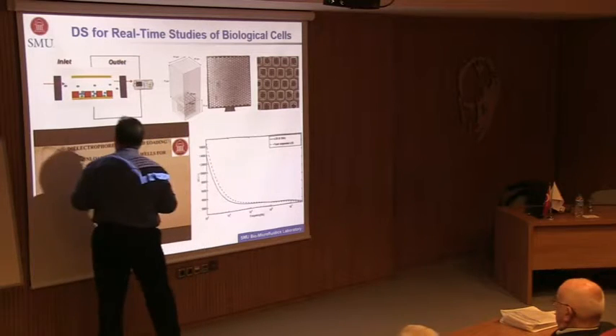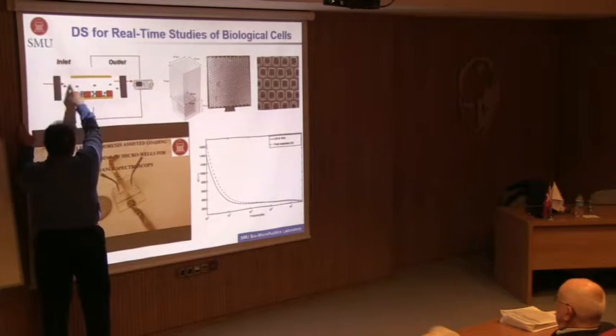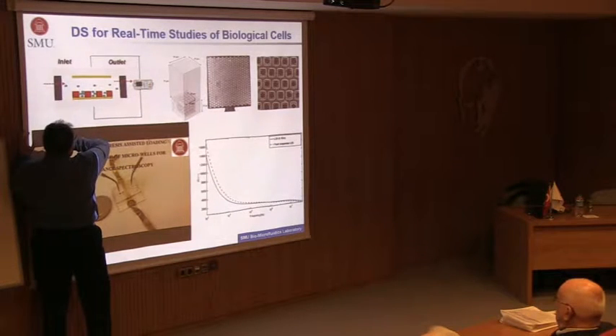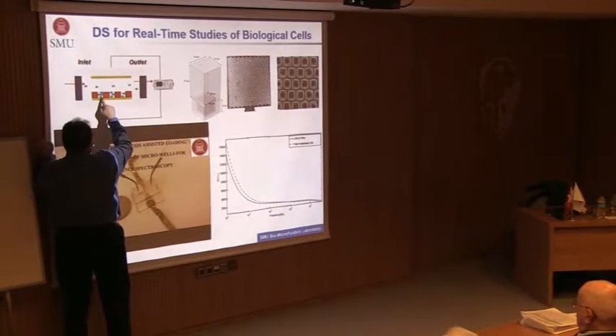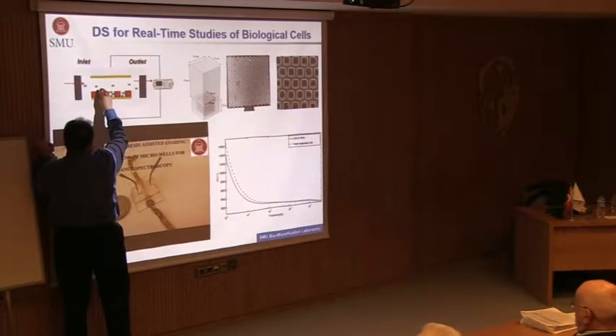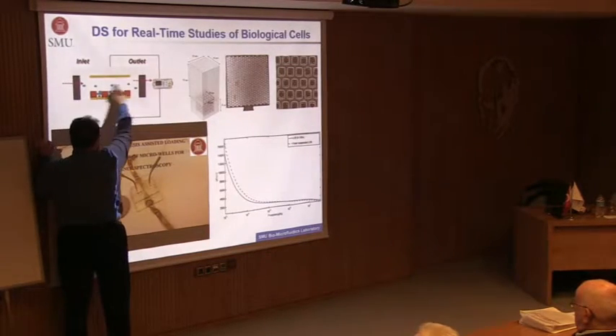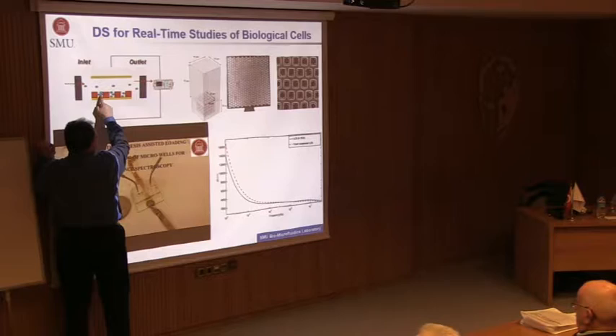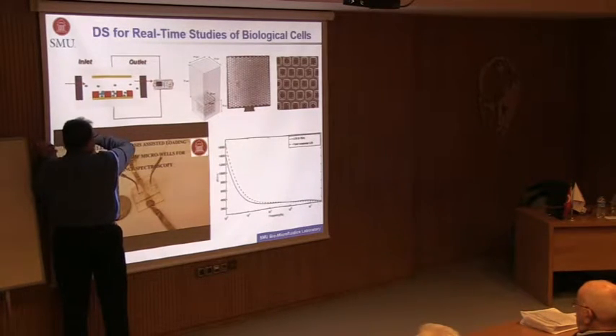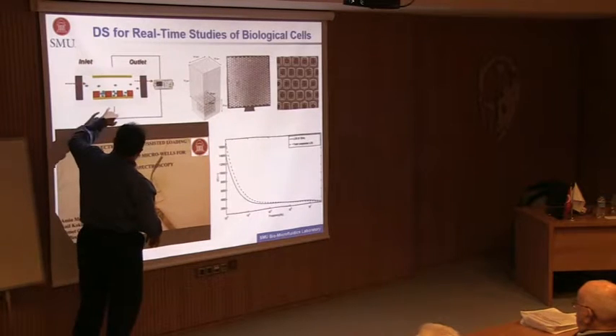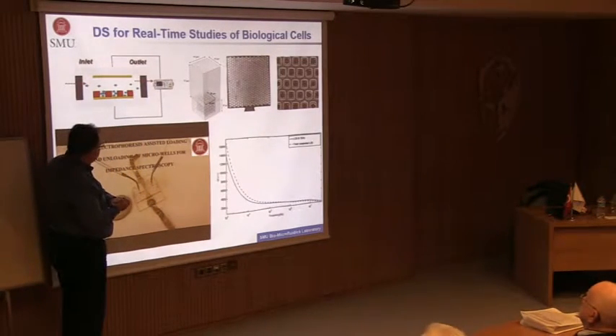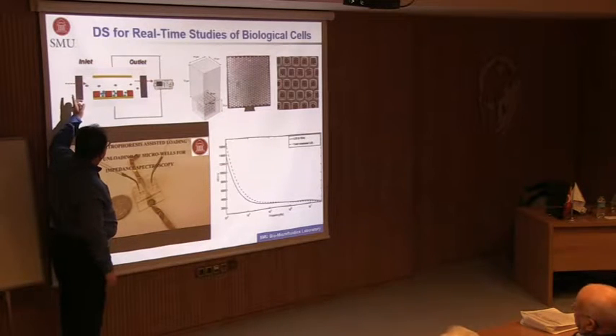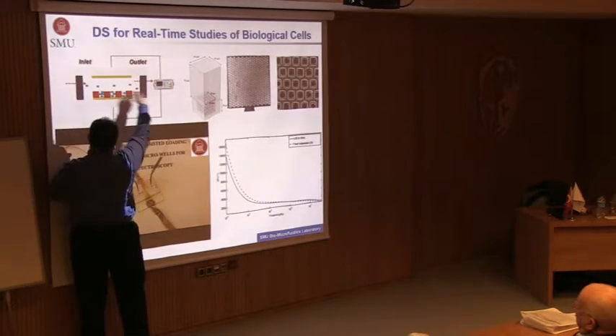And because these are electrodes, as the particles are passing by, if I apply a correct frequency here, I may induce positive DEP. Why? Because electric field lines are going to come here, and that means there are large electric field gradients. I can capture cells that are flowing by in the wells. And then I can stop applying the electric field and connect this to an impedance analyzer and obtain the electrical impedance, make my measurement, and then I'm going to actually switch the electric field to a different frequency. If I see negative DEP, these particles are going to get out and will be washed out.